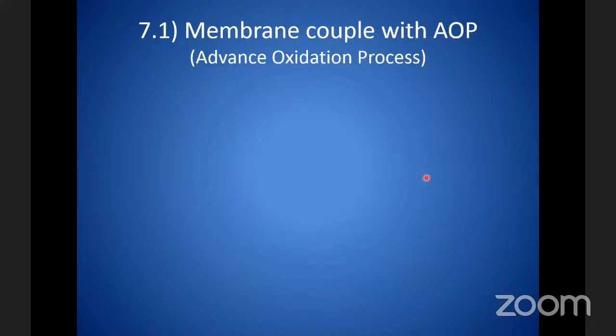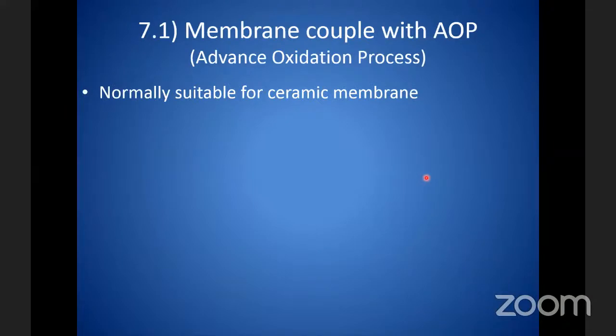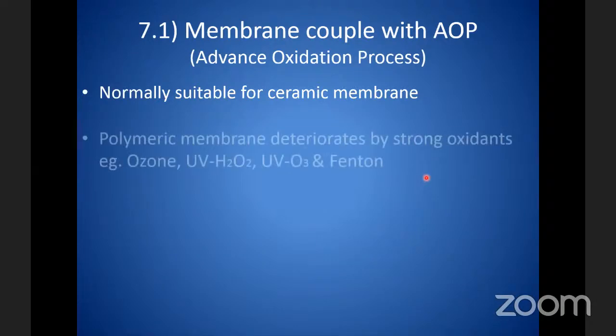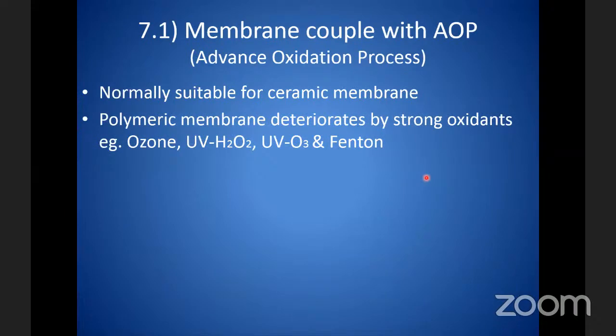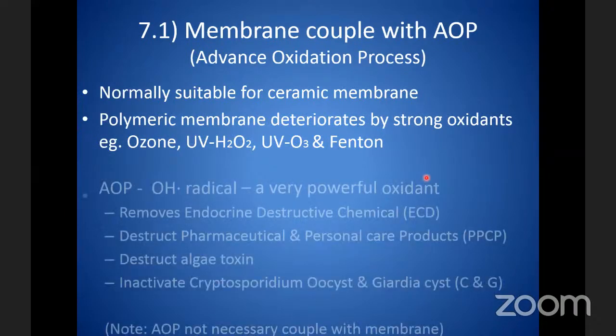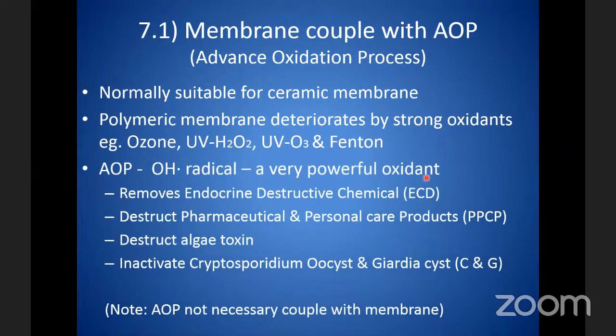So membrane coupled with advanced oxidation, as I said just now, is normally suitable for ceramic type of membrane. If you use polymeric type, it may damage your membrane, because polymeric cannot stand the strong oxidant. As I explained, the strong oxidant is normally this OH radical that oxidizes the organics. It can remove endocrine disruptive chemicals, normally by destructing them. It will oxidize the organic pollutant.